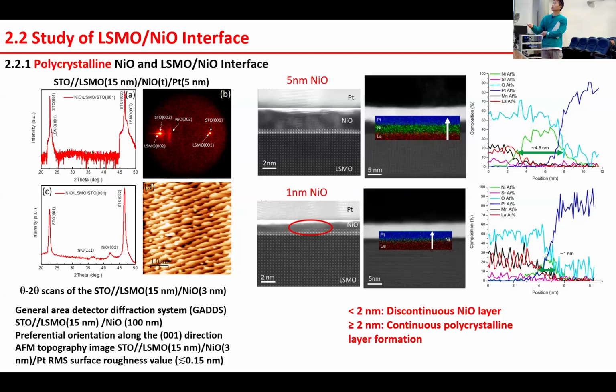I understand. This image is just to clarify. Here the interface of the nickel oxide and LSMO is not quite continuous. We cannot see because the resolution is still limited. The red here just shows that the nickel oxide is discontinuous, not a flattened interface. That's all. Okay, not so much from the image. Yeah. Okay.